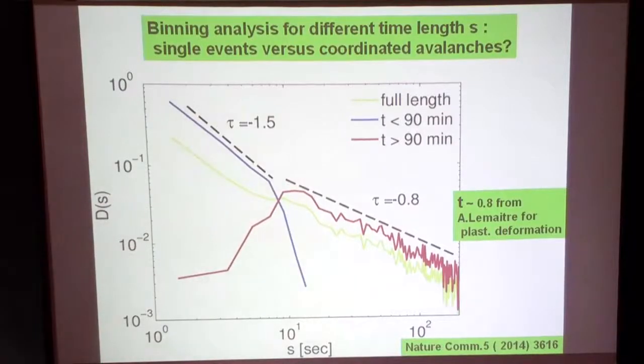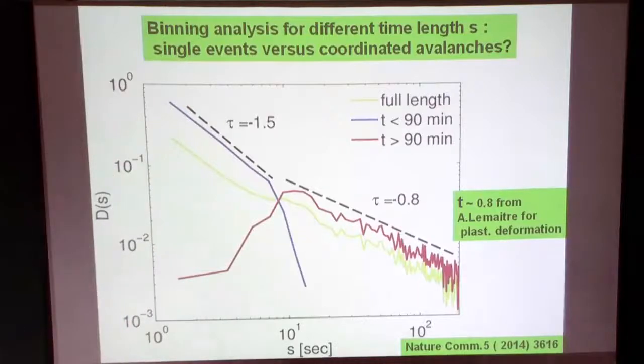So the idea is that we have these local, randomly oriented events, and then they form the shear band. Whether that is true or not, I don't know. We had the discussion before, right? On several occasions. So it's still an open question for me. But it would be very interesting to learn more about this crossover. Do we reach a critical density of these local events, and then they interact due to the long-range stress field in a coordinated, almost synchronized way, or is it just a domino effect, where you tilt one, the next one is tilted, and so on?